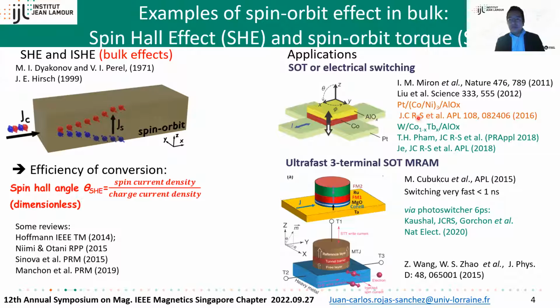And this was indeed shown by the pioneering work of Ioan Mihai Miron and Luqiao Liu, where, for example, we sweep an in-plane current. Under the right conditions, we can manipulate or switch the perpendicular magnetization of this cobalt nanodot. This switching is very appealing for application because it's fast, below the nanosecond time scale, and then the three-terminal spin-orbit torque MRAM was developed.